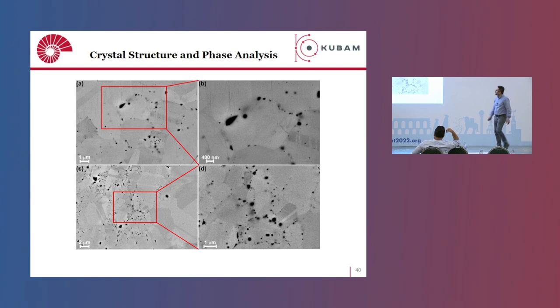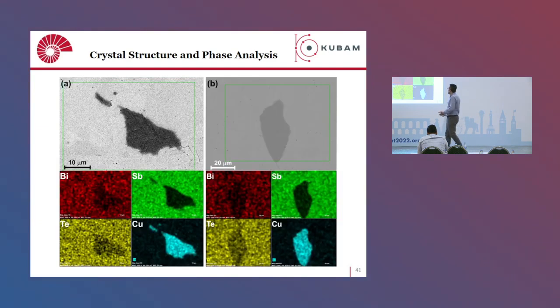Okay, here is the microstructure. You can see nicely that these are the grain boundaries, well-resolved grain boundaries. And at the grain boundaries, we see mostly copper telluride. The copper telluride that we introduced is mostly decorating the grain boundaries. This is good because it is a metallic material, which might help with the electronic conductivity, but at the same time, it is a secondary phase, which can lower the thermal conductivity.